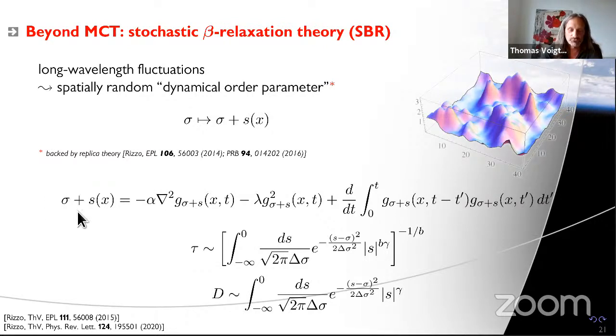If you set the distance to the glass transition to 0, and this term was also not there, then you have g squared equals the convolution of g with g. It's easy to convince yourself that power laws are the solution of this equation, and hence the famous power laws of mode coupling theory. Now the idea that Tommaso came up with, and you can read about in his papers, is that there is a rigorous argument, borrowing ideas from replica theory, that what should happen beyond a mean field level, in a certain sense, is that there need to be fluctuations of this, if you like, dynamical order parameter. So whatever was a constant sigma needs to be a spatially dependent fluctuating quantity.